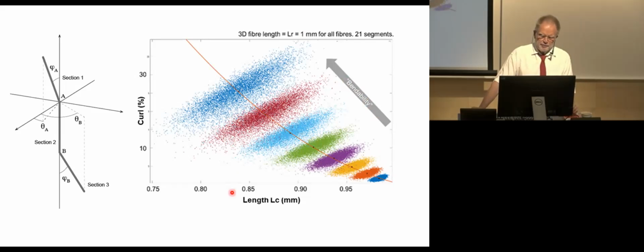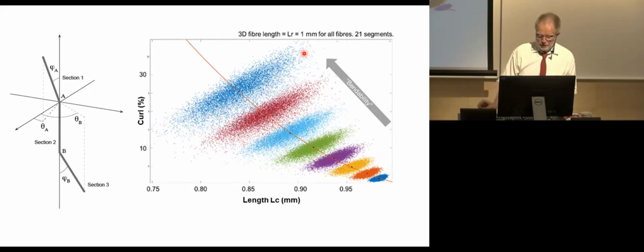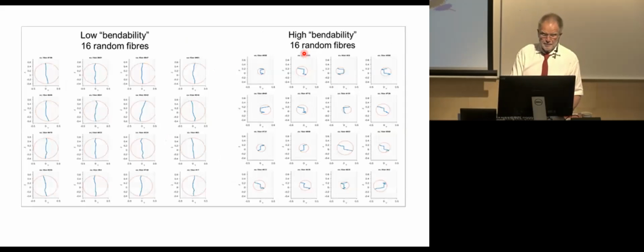So by going by the photos, we were actually drawing the wrong conclusion about what happens with the fiber. And sometimes it could be a process where they get more curled, but they get longer at the same time, having the same average fiber length as a number, but they could be very curled and looking different. If they look very straight here, they are just much shorter, and if it happens to be a photo taken from 90 degrees, much longer. So just measuring something like length is not easy.